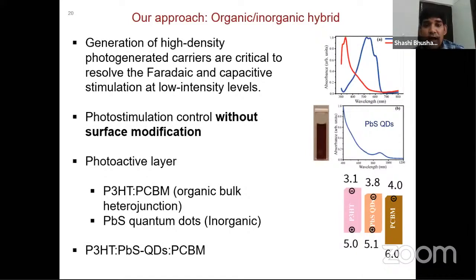And what we saw, if you see, we used here P3HT:PCBM as an organic polymer. P3HT is the organic donor polymer, and PCBM is the organic acceptor small molecule. In mixing these two, you can see from here that the P3HT has good absorption in the range of 400 to 700, that is the visible region, for the eye perceiving anything.